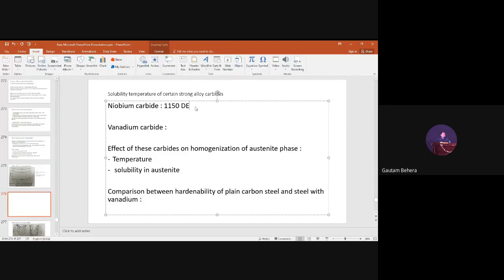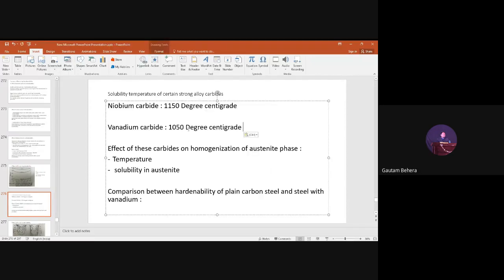Okay, anyways, degree centigrade, and this is 1050. That means you can understand this niobium carbide is still stable up to this temperature, and vanadium carbide is still stable at this temperature, right? But basically we do austenitization at a temperature of suppose 950 degrees centigrade or 850 degrees centigrade or 900. That means even at austenitizing temperature, this carbide will be still there.